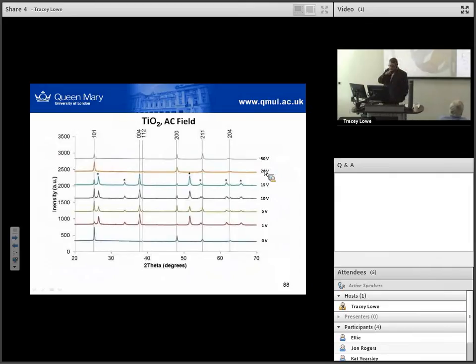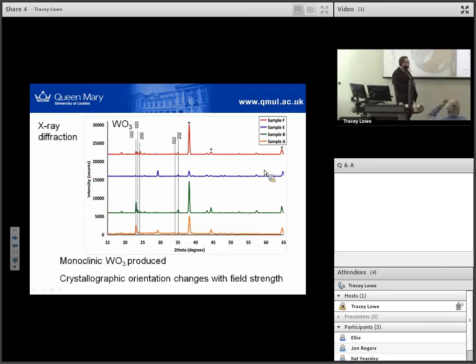If we look at the titania sensors we produced, we can see changes in the relative orientation or relative intensity of the different peaks of our material. These starred peaks correspond to the gold electrodes and the alumina chip substrate. Depending on the electric field, we might get a larger 004 peak than the 101 for our anatase titania.